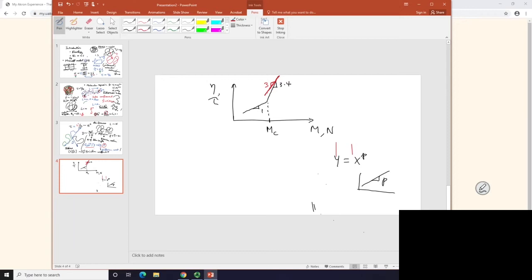And of course, there was a lot of puzzle or confusion about whether the theory really is adequate, because you didn't show it was 3. It was not 3, it was 3.4 as experiments found. But today, I think everyone accepts the basic notion that you capture the basic part. There were lots of efforts made by making samples with sufficiently high molecular weight to show that eventually it approaches the power of 3 instead of 3.4.